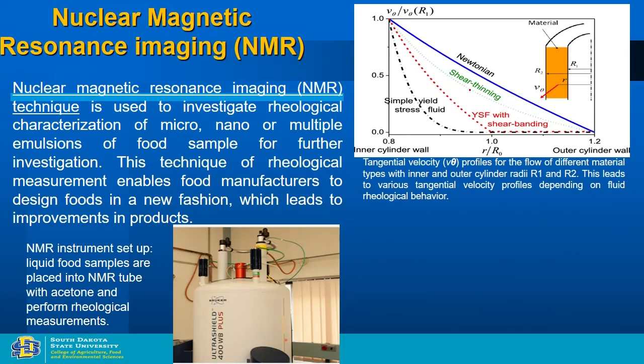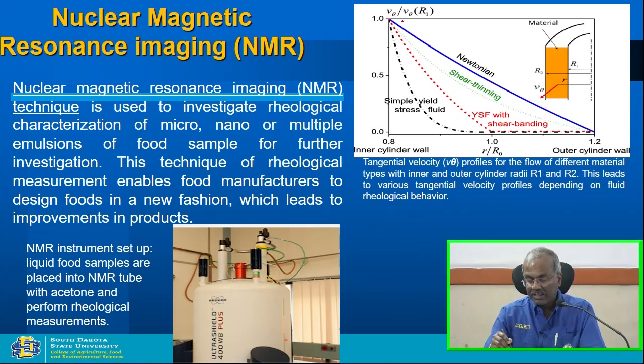And these are all the tangential velocity profiles for the flow of different material types with the inner and outer cylinder radii R1 and R2. This leads to various tangential velocity profiles depending on fluid rheological behavior. So they looked at the NMR and can see that Newtonian fluid behavior is straightforward here, and then you have shear thinning and also shear banding, yield stress fluid with shear banding, and also simple yield stress fluid over here. So this is where they are trying to correlate the rheological behavior by using nuclear magnetic resonance imaging. This is a new way of thinking and looking at the fluid flow profiles, and that helps them to understand what is happening with the material itself.